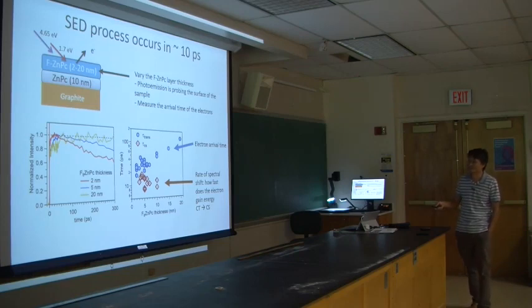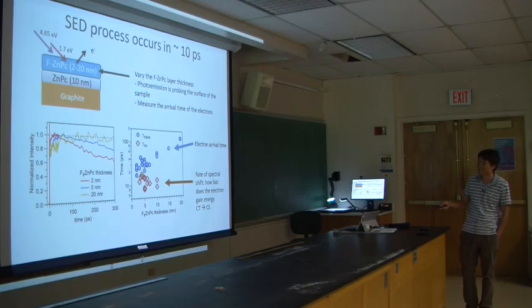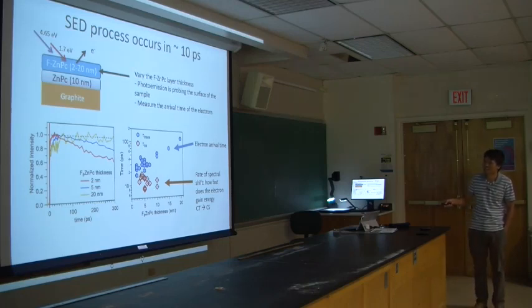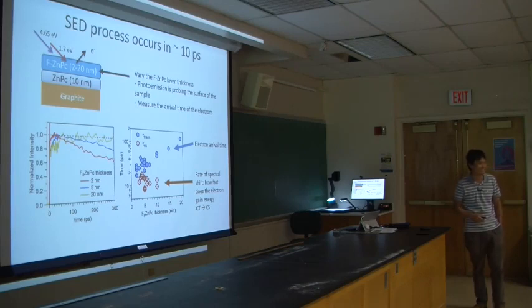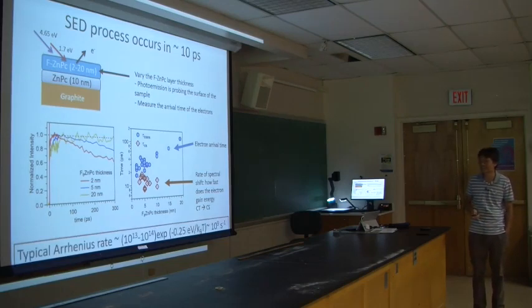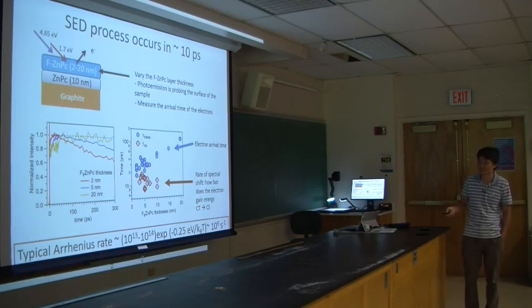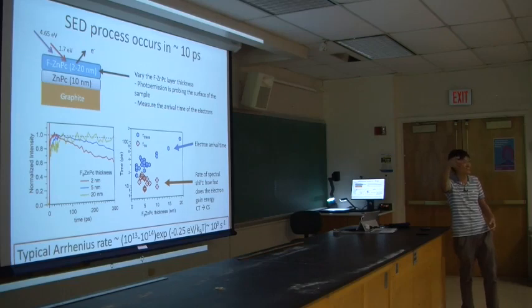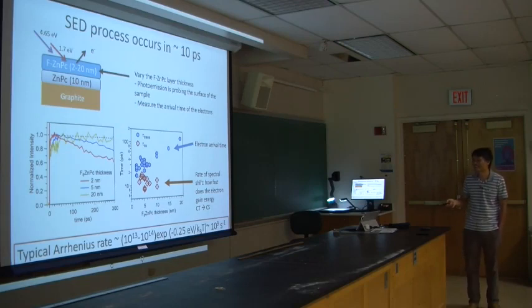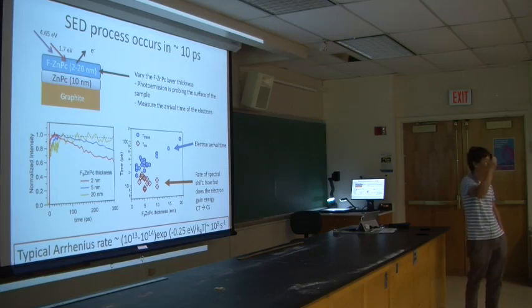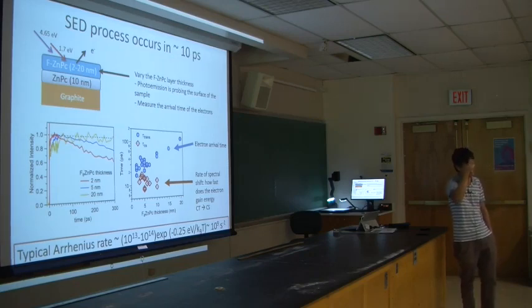Of course, for a thicker film, we can't really see this bound CT state, right? So that's why the data stops here. Anyway, these are on the 10 picosecond, 20 picosecond time scale, right? So it's very fast. Why would I say it's fast? Because if you use the typical thermally activated rate, these exponential terms, minus the activation energy divided by kBT, right? Then you get a rate of about 10 to the 9, so nanoseconds, right? So this is 2 to 3 orders of magnitude faster than the typical thermally activated rate. So what happened, right?